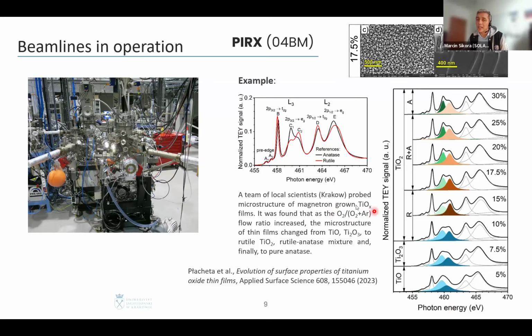So in this work in Applied Surface Science, it was possible to probe several samples with different composition of the gases that were present in the sputtering chamber of magnetron sputtering. The samples were ex situ inserted into the analysis chamber of the PIRX beamline and probed with high quality. And it was quite clear that depending on the ratio, if you look to optimize the amount of anatase, you have to really go to a high amount of oxygen in the atmosphere.